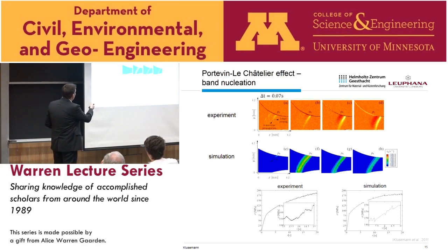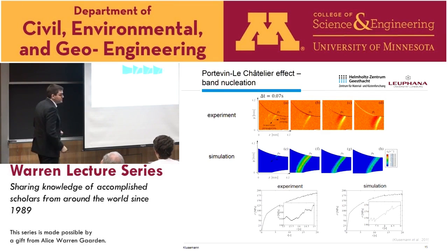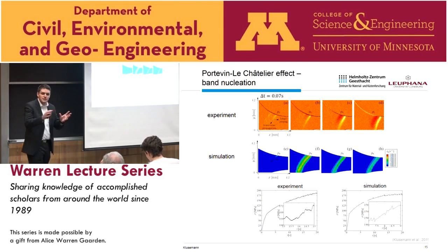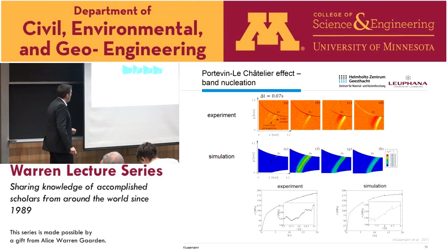Okay, so first of all we investigated the nucleation behavior. That was the first step. On the top here you see some experimental results. The time step between these different pictures is 0.07 seconds. The same holds for the simulation. Of course a different time stage, but the time shift is always the same. And what we looked at here was in particular how the PLC band behaves during the nucleation with respect to longitudinal and transverse propagation.